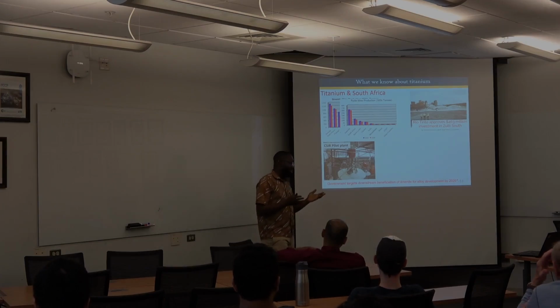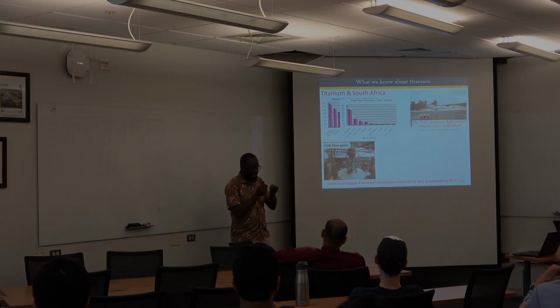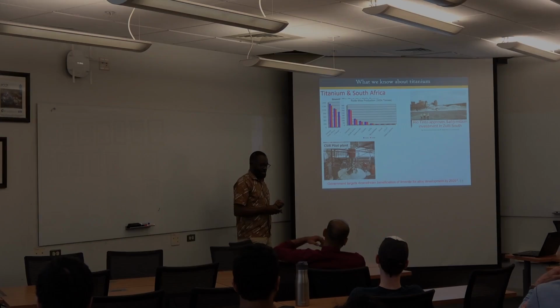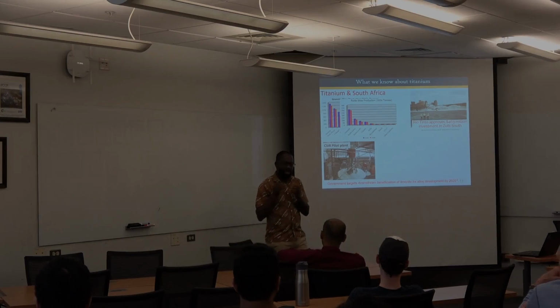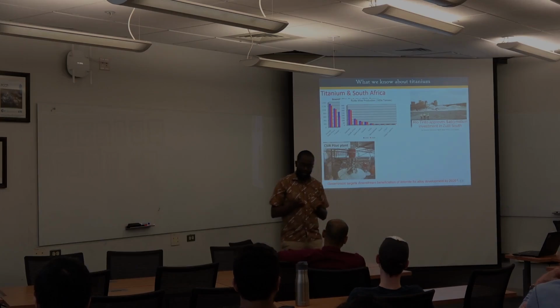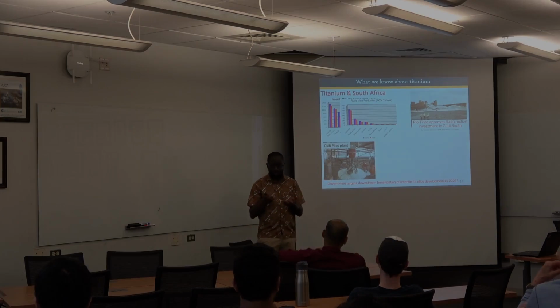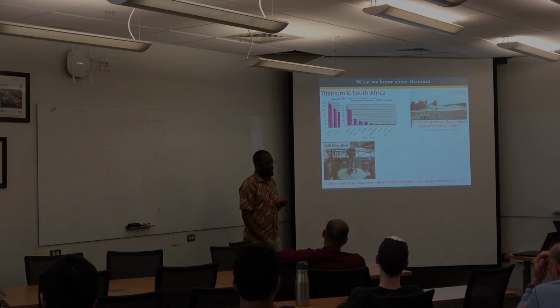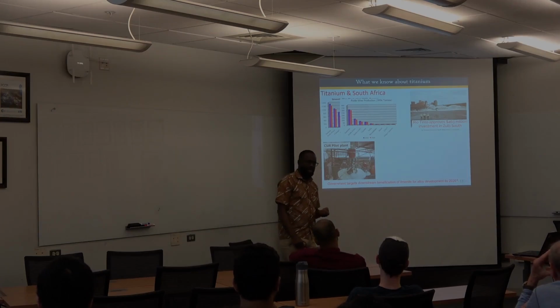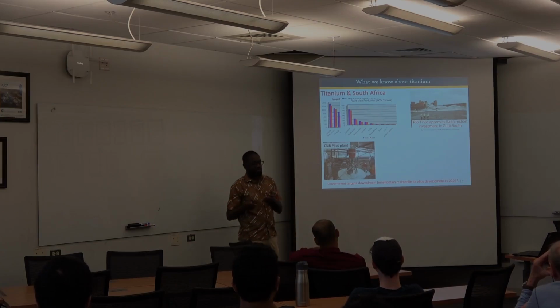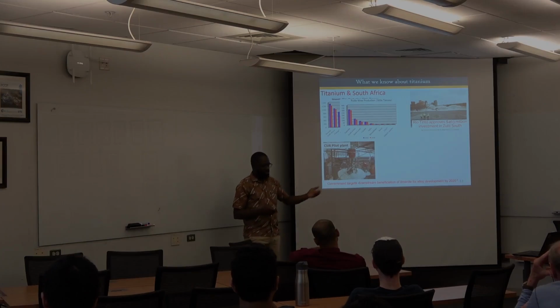I got a bit delayed in my work around that time because we wanted to use that powder for alloy development. But we only got a few, and we characterized them, and we saw that it has a high amount of iron in it, and that was one of the problems, and other impurities basically. So can we really add value to this iron-containing titanium powder? That was what actually drove me into developing low-cost titanium alloys.